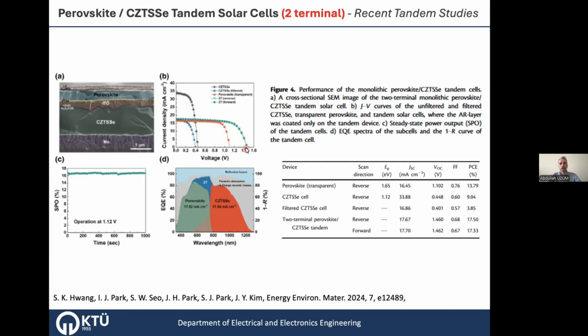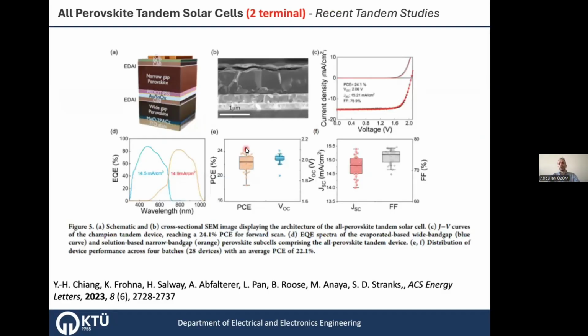The others are, for example, all-perovskite tandem solar cells. In this kind of solar cell, you have a perovskite bottom cell and, again, a perovskite top cell. Because, as I said, it is tunable, you can tune the band gap. You can use a low band gap perovskite material for the lower cell and a high band gap perovskite material for the top cell. And here, the recombination junction is, again, a very thin layer, a thin gold layer with the tin oxide layer.